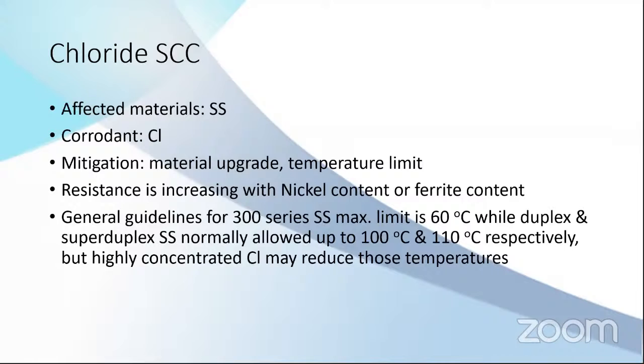So this is the general guidelines of the application. So if you have 304, 316 series stainless steel, the maximum limit is 60 Celsius. And when you're using duplex, it can have allowance to 100 Celsius. Super duplex can have 110 Celsius. But this is just general guidelines. If you have a specific application, you need to consult with the corrosion engineer if this material still can be used or not. This is just a general rule of thumb.